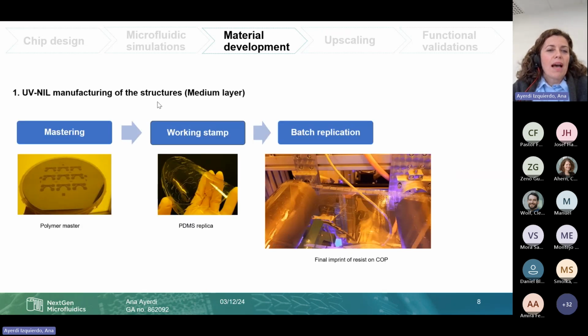As for the manufacturing of the middle layer, two strategies that were compatible with roll-to-roll manufacturing were followed: UV NIL imprint and extrusion coating. In the UV NIL strategy, a polymer master was fabricated, from which a PDMS replica working stamp was obtained. And here we can see an in situ monitoring of how this batch replication looks within the roll-to-roll production line.